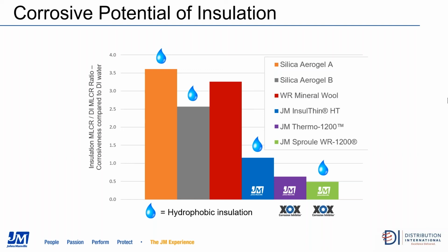But you can see the various results in this test. Again, lower the better. So what we see is JM has two products there towards the right side. The green one is our perlite. That's hydrophobic. The one right next to it is Thermo-1200, which is water resistant. And then you compare it to the other ones. What's different about these products? And the difference is the XOX corrosion inhibiting chemistry. So that's the third factor.